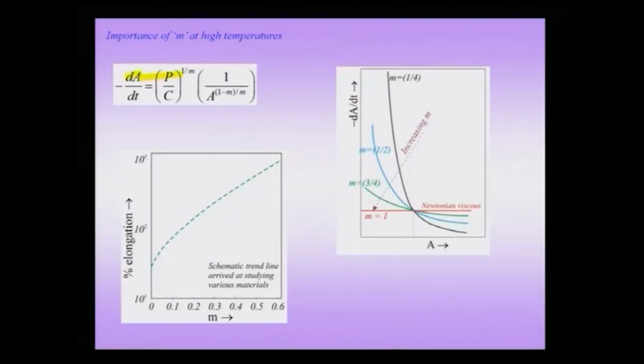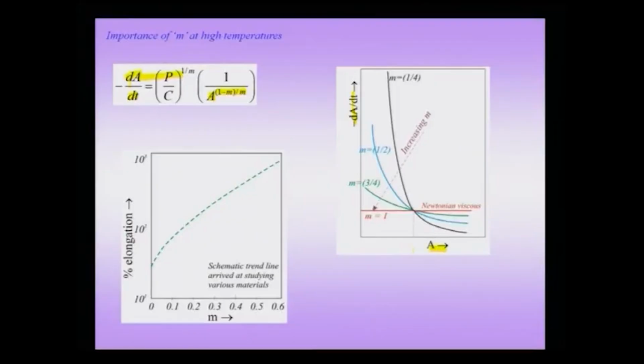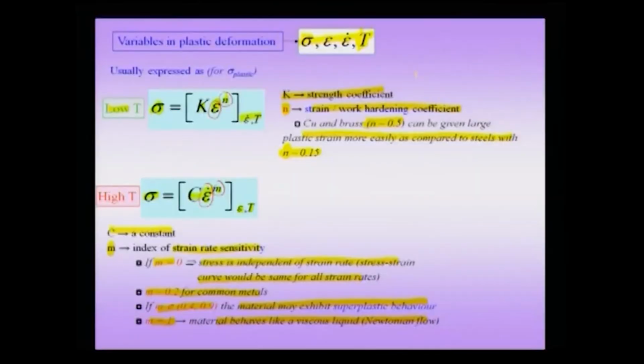So, I have seen from previous relations that dA by dt can be related to A with the power (1 minus m) by m. If I plot dA by dt, which is the left hand side of this equation, the reduction in area per unit time, versus A, and compare different materials with different m values, actual materials will be close to one of these curves. If m is 1 by 4, 0.25, which is in the range where typical metals lie, we see that for a given area, the reduction in area is large. On the other hand, if I had m of a higher value, the increasing m curves go from here to here along this dotted line, as you can see.